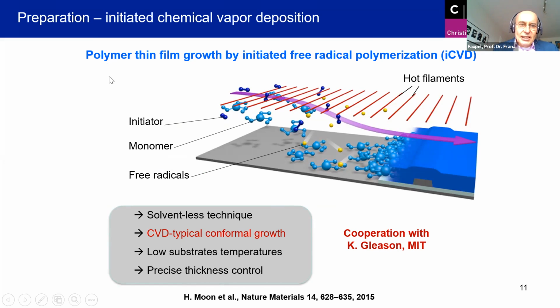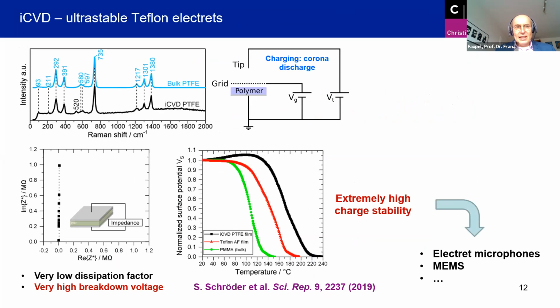And then you take initiators. Initiators are molecules which have, for instance, a peroxide bond, which can easily be broken at mild temperatures. And here in the gas phase, we use hot filaments to break up these initiators to form radicals. And then, like in the wet chemical technique, the radicals interact with the unsaturated bonds in the monomers, and then you form an organic film. This is a solventless technique. You have much more opportunities compared to wet chemistry. You can get a conformal growth. You can do the process at low substrate temperatures. That's particularly interesting. And you have very precise control over the thickness of the films and other parameters.